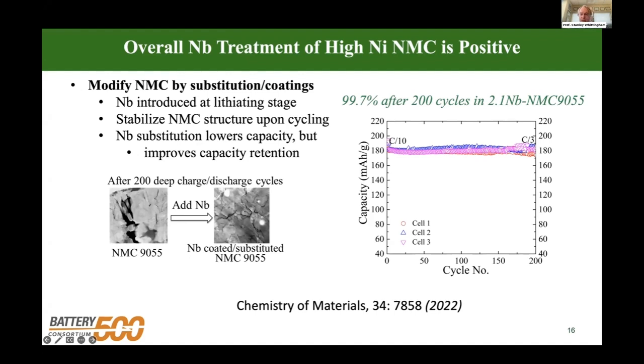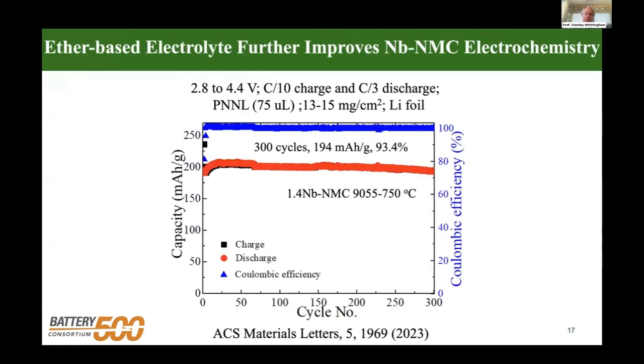So we're not getting extra reaction of the electrolyte with the surface of the materials. And this again is in a carbonate-based electrolyte. And you can see these are 3 different cells, very stable over 200 cycles, essentially no capacity loss. But I say this is again with the carbonate electrolytes. What we've been doing is switching away from those because carbonates are not good for lithium electrode deposition.